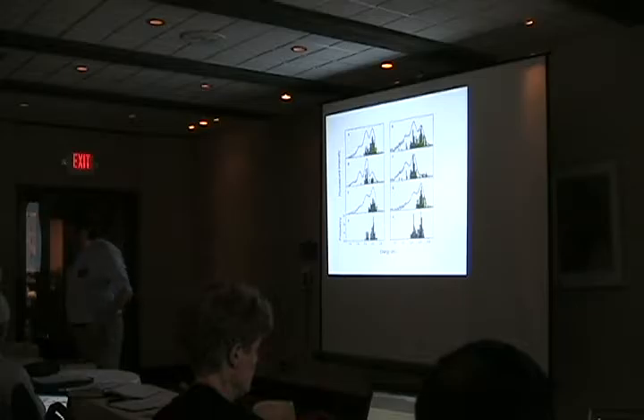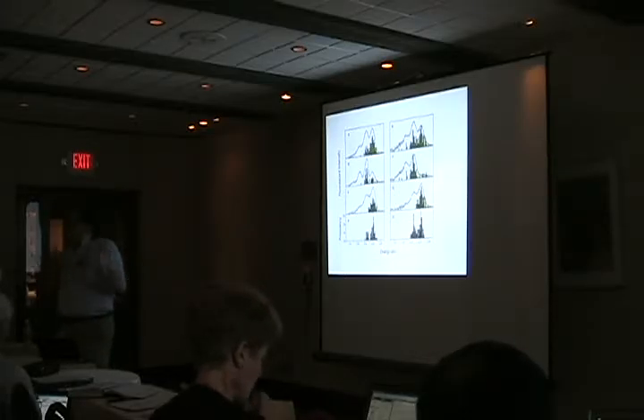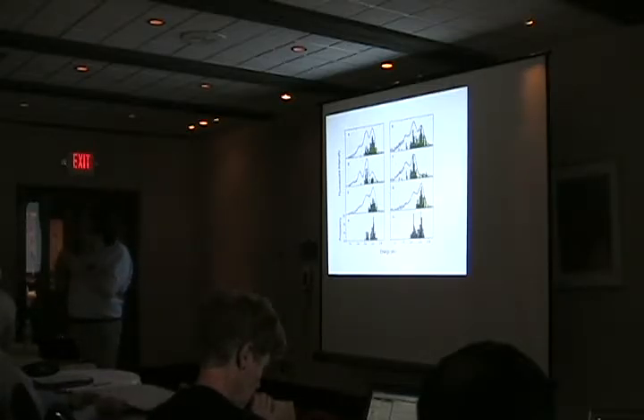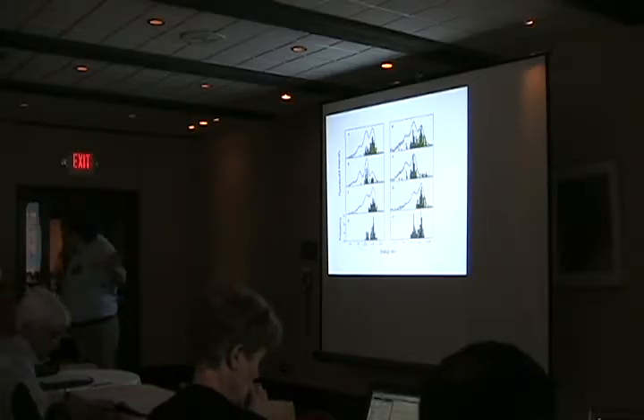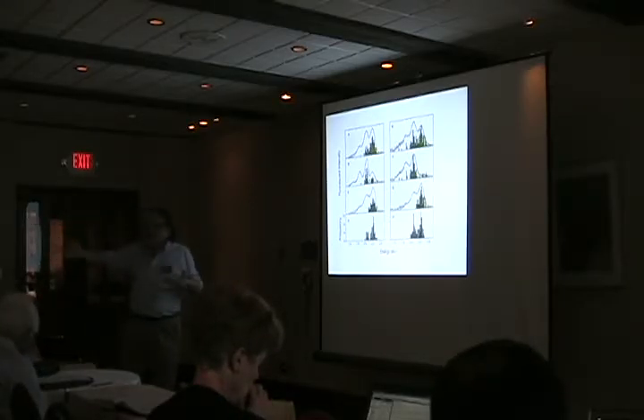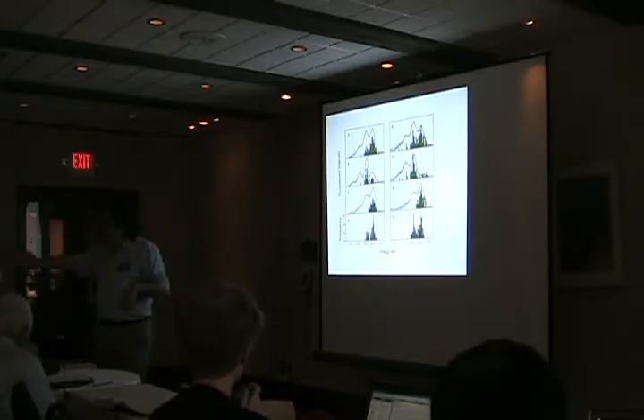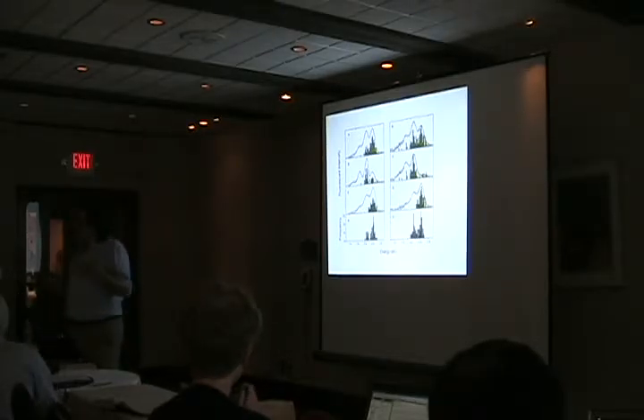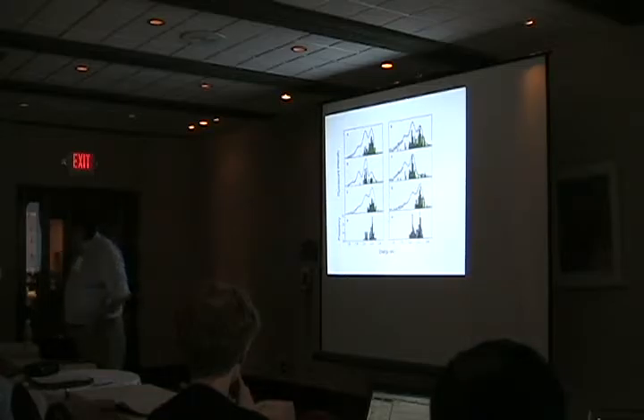The question I have then is, if it's so, why, even when you make the chain short, don't you get any exciton transfer between chains? They're right there. I'm sorry, that's a really good point. So in the bulk polymer with no added PMMA, a short chain and a long chain give the same spectrum. Absolutely. In fact, Keith brings up a beautiful point. The long and short molecular weight on a pure film is the same thing, except if you get it so short that you disturb the quantum delocalization along the chain. But that would be very short. That would be 10 nanometers.